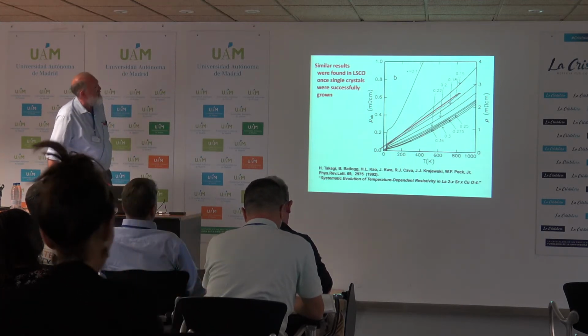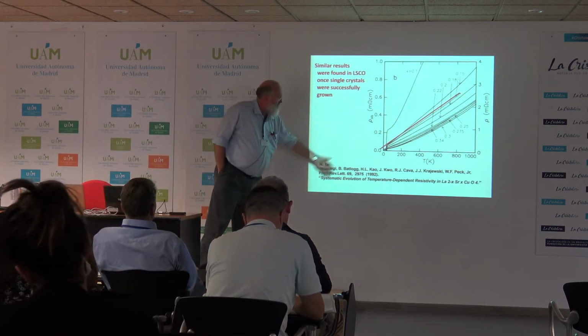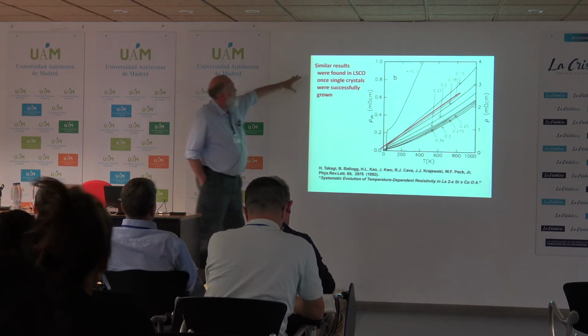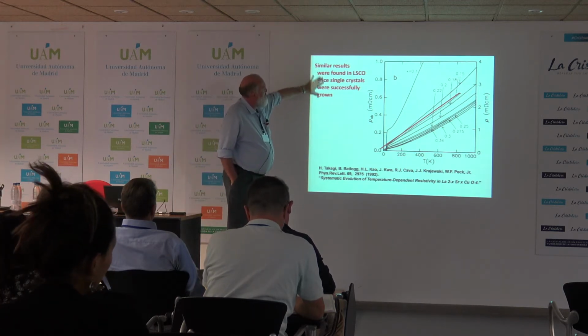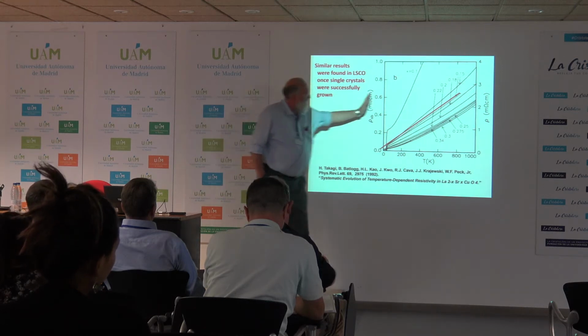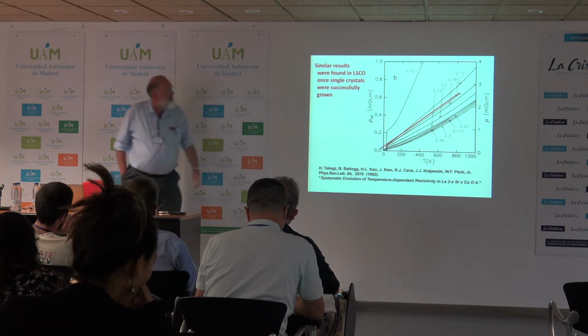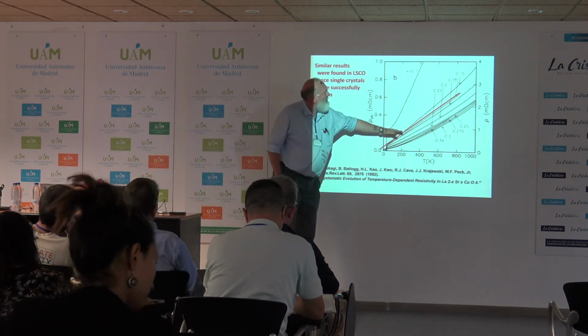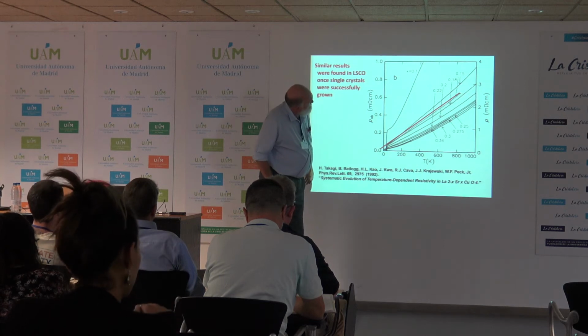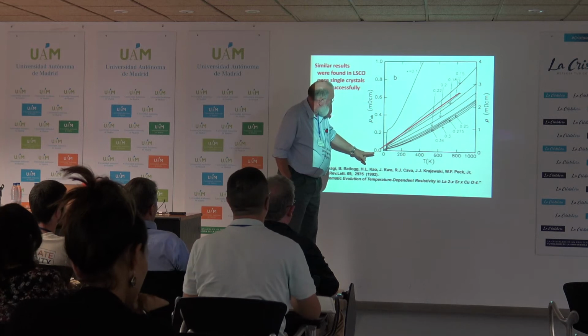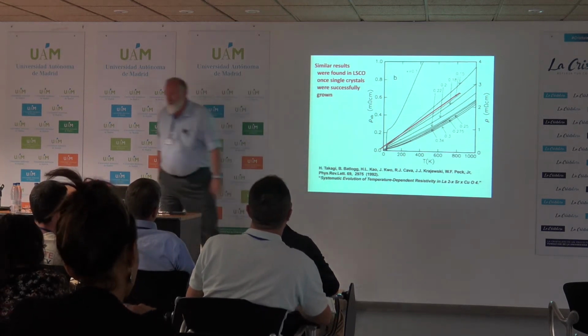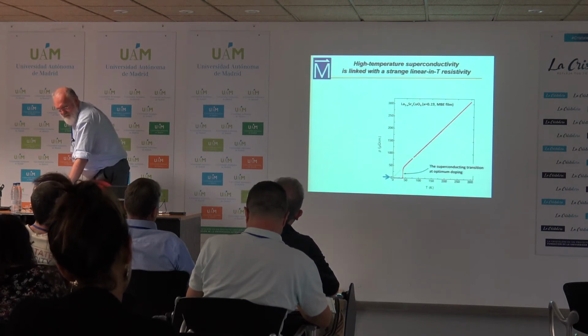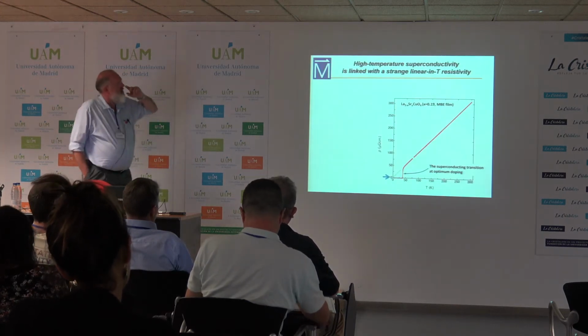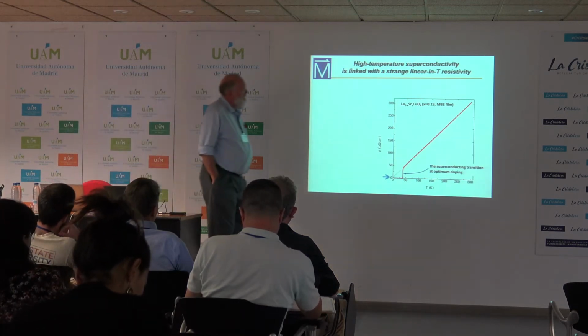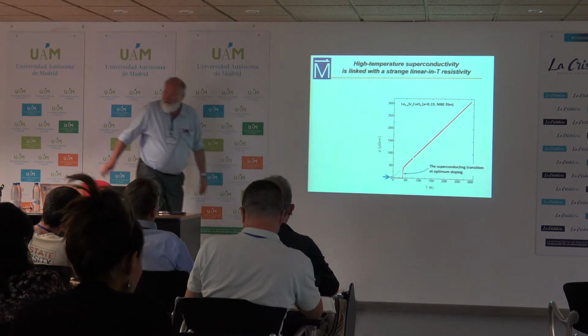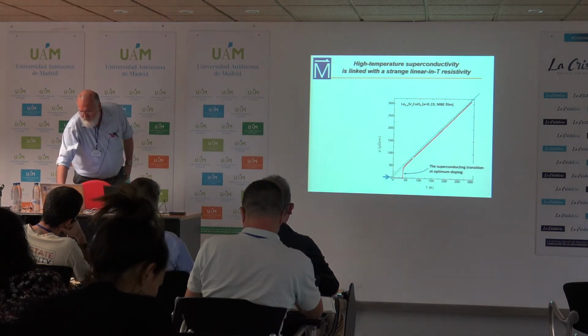This is like data that Tony Carrington showed. This comes from Hide Takagi and Bertram Batlog's work from '92. This is LSCO. Here they can control the doping with strontium concentration. Once they were able to make single crystals, they could then do the systematic behavior of transport, and you get the best linear behavior at optimum doping here at 0.18, 0.17, I think, but I didn't see it labeled. And you see the finite extrapolation for this material that's somewhat dirtier than YBCO. So this is now the state of the art on lanthanum strontium copper oxide at 0.19, linear temperature dependence, and the intercept is very close to 0, certainly within our ability to extrapolate.